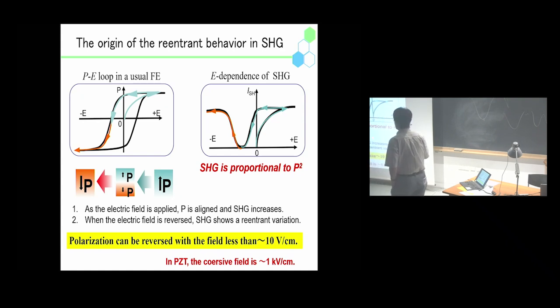At this point, the electric field is about 10 volts per centimeter. For example, in PZT, a famous conventional ferroelectric, lead zirconate titanate, the coercive electric field is about 1 kilovolt per centimeter. So the coercive electric field here is even smaller than in the usual ferroelectrics. That's the second message about these materials.